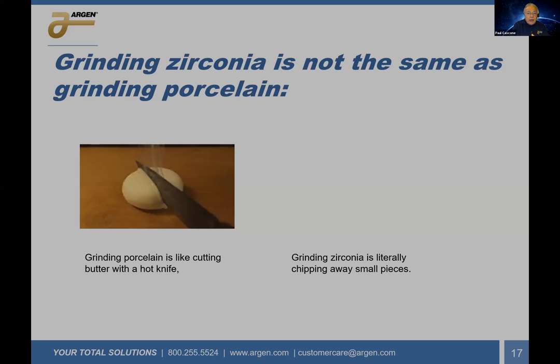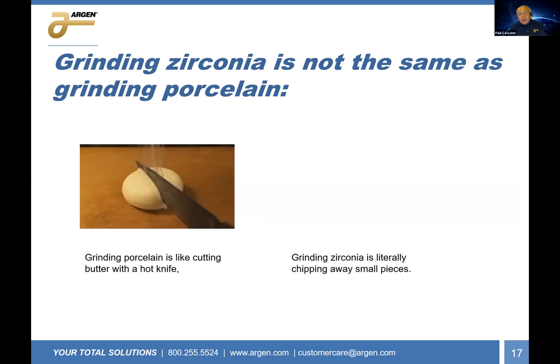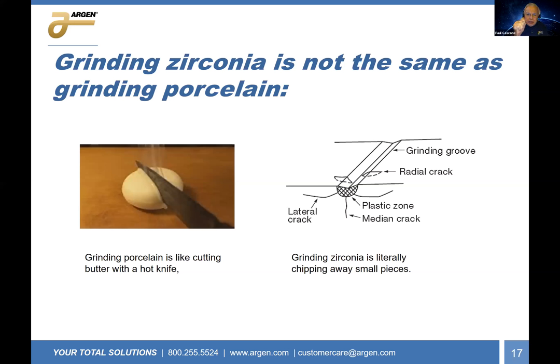Now, when you made an adjustment on porcelain, on a PFM, for example, that was relatively easy. That's like a knife going through butter. But when you're trying to make an adjustment on zirconia, what you're actually doing is making little chips off the material, because the material itself doesn't carve. It actually fractures. You see, here's a score on zirconia, and these little radial cracks, when they come to the surface, they chip off. That's the little thing that you see flying off, or you may feel it flying off. If you see sparks, then you're witnessing the transformation of zirconia, and that unit may not be long for this world.